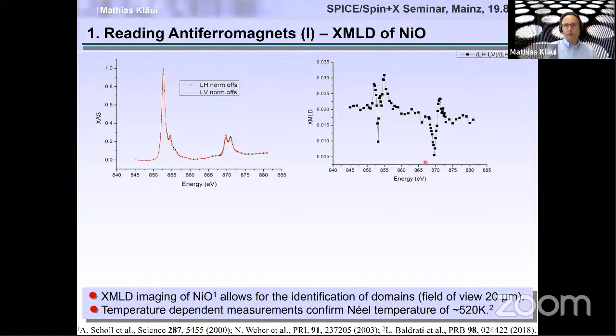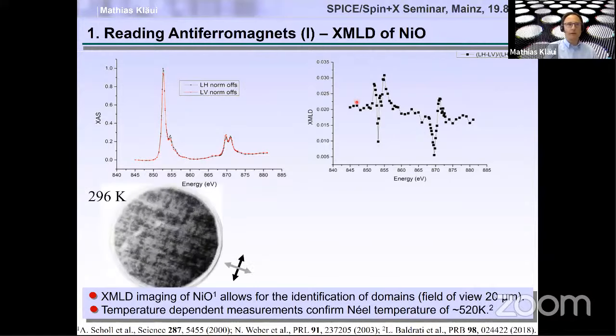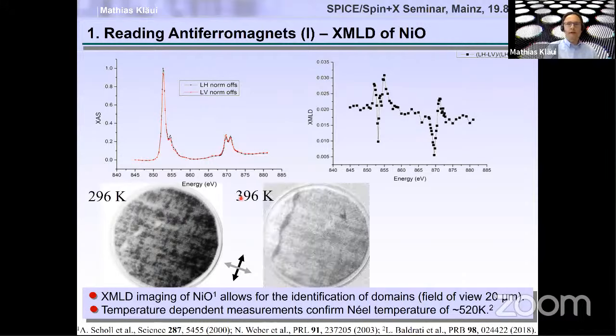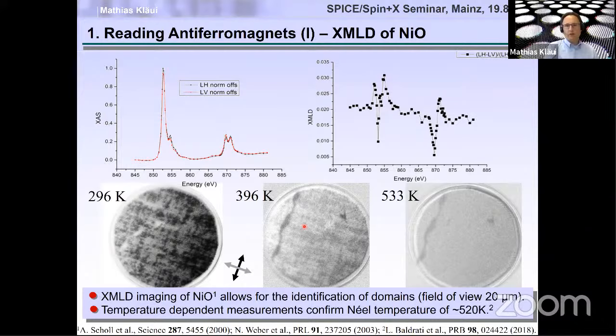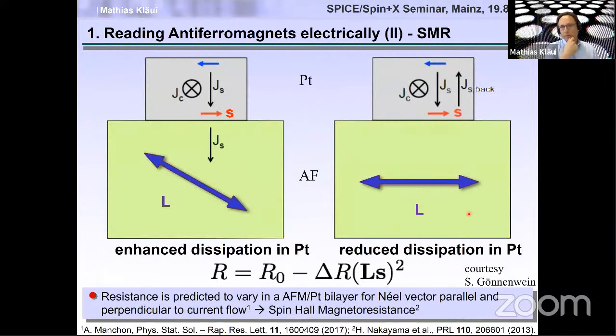So this is a typical X-ray magnetic linear dichroism spectrum that you see here, and you can use that to do imaging. And then we see, for instance, at 296 Kelvin, so this was one of the first samples that we had, you see these relatively small domains, and there are many of these domains. If you then increase the temperature, then the contrast goes down, and eventually at the Néel temperature, the contrast vanishes. What you still see here is some topographic contrast. Okay, so this allows you to do direct imaging, but the problem is that this can only be done at the synchrotron. Now, an alternative is electrical readout, and this is based on what is called spin Hall magnetoresistance.